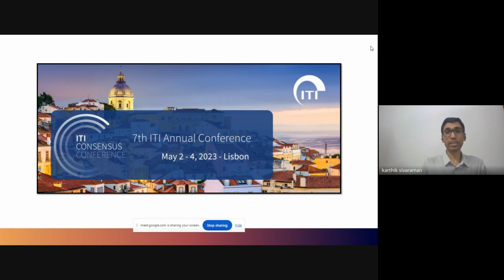Another equally important thing is that the marginal bone loss which was seen with the new commercially available zirconia implants was just 0.67 millimeter, which is much less than the around 3 millimeter values which were observed previously. The fracture rates for the one-piece zirconia implants were also as low as 0.2% with the new commercially available zirconia implants. So these were the important consensus statements which one can go through.